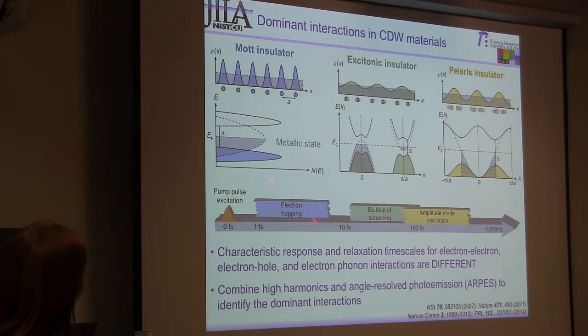And then I talked a little bit about these charge density wave materials. This was a collaboration led by Michael Bauer and Stefan Matthias, and we helped them with the harmonic sources to do photoemission, to just see if you take one of these materials that has a charge density wave order, like you can see best here, where the electron-electron interactions are strong enough that the lattice goes into these pairwise, the lattice period doubles, and the electron distribution localizes, and that's an insulating state.